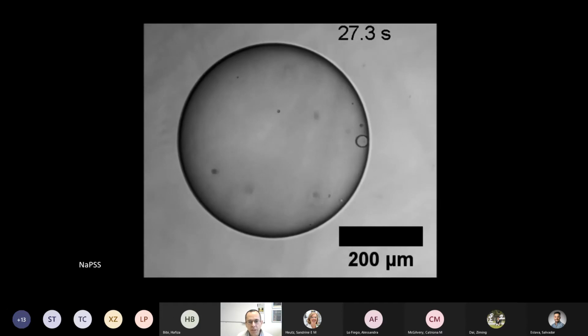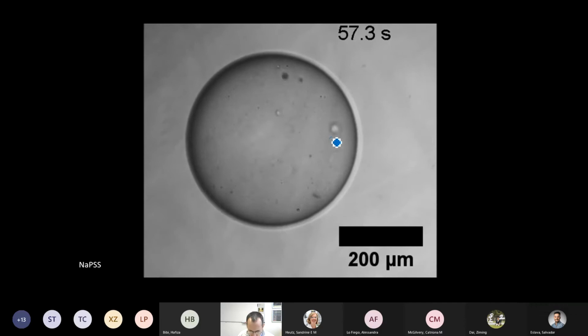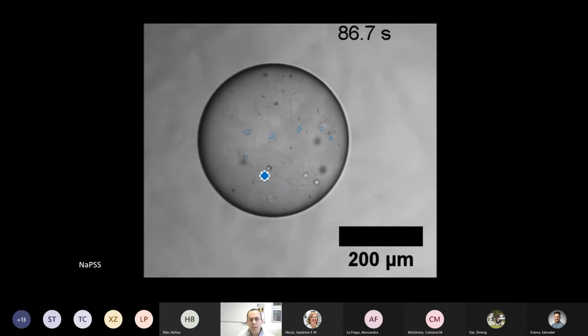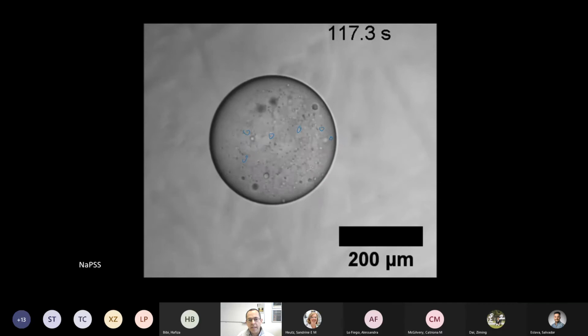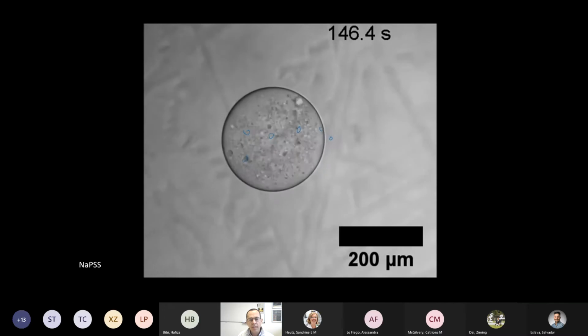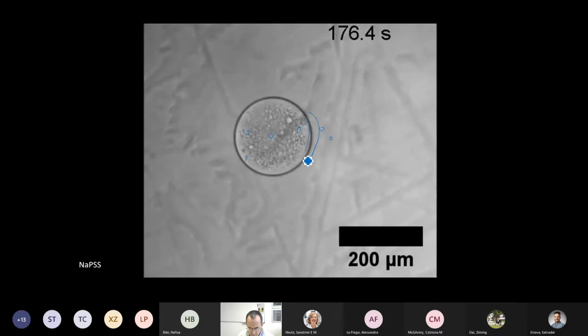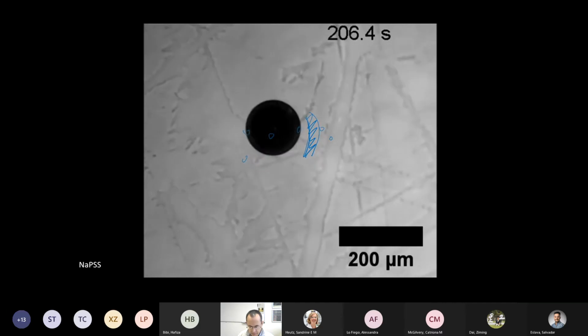Just to recap what we saw earlier, here you see a number of droplets inside that are clearly, I guess the word we would use is nucleating within this fluid, as well as the fluid shrinking, as well as, we found, forming a skin, presumably at some point if the process is fast, and eventually solidifying in some kind of directed solidification way. So there's a lot of physical chemistry going on here, and at multiple scales. So clearly from the molecular scale, it must be crossing some kind of phase boundary, and there a glass transition or, I guess, a gelation process, and eventually some kind of demixing probably as well.